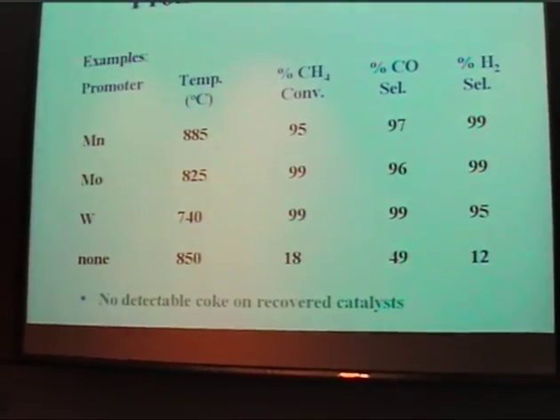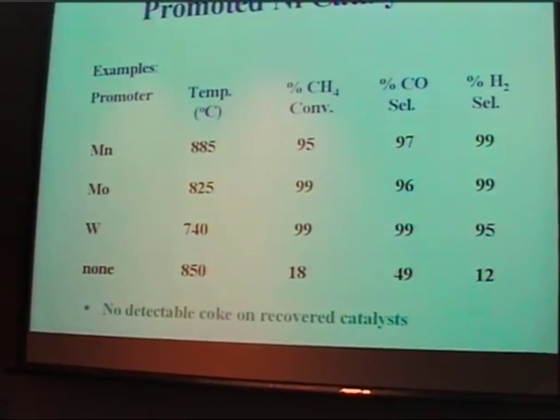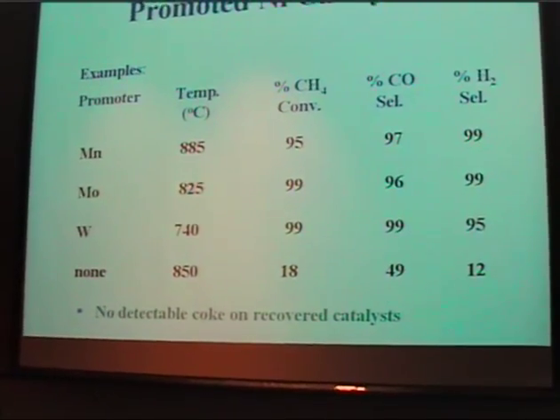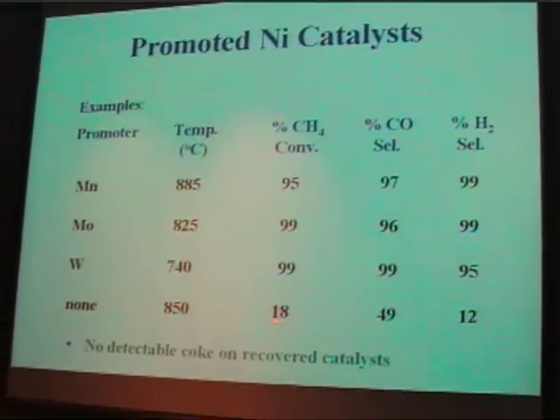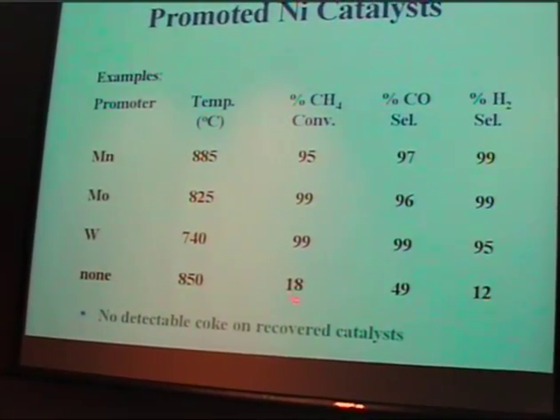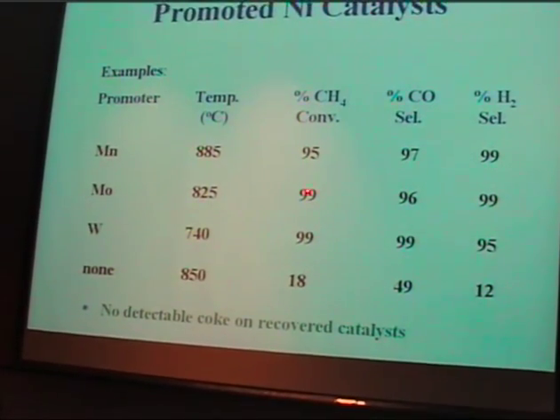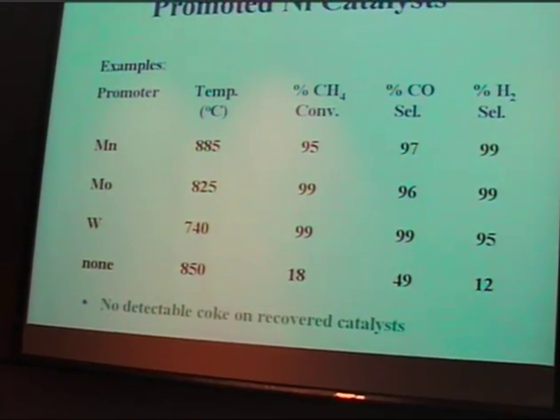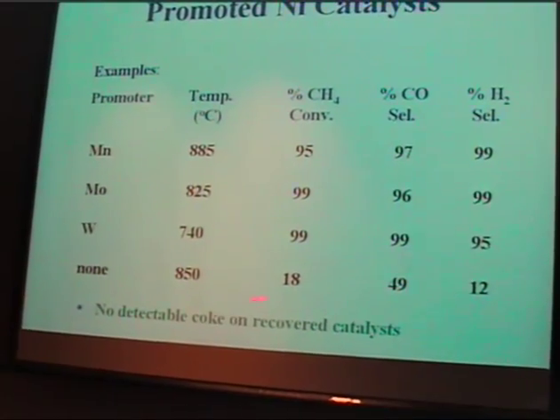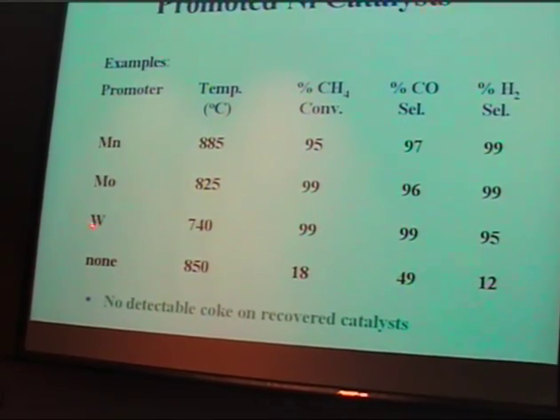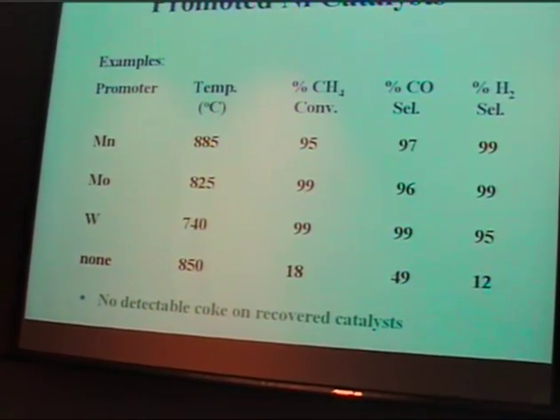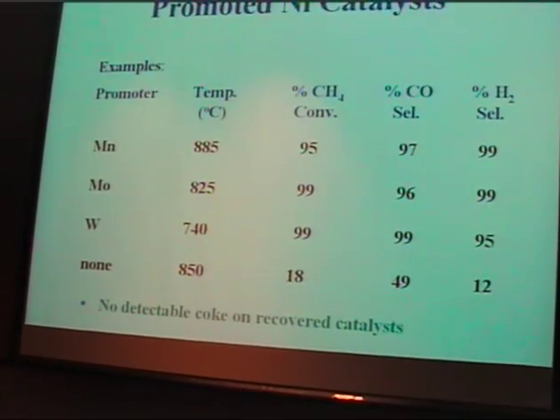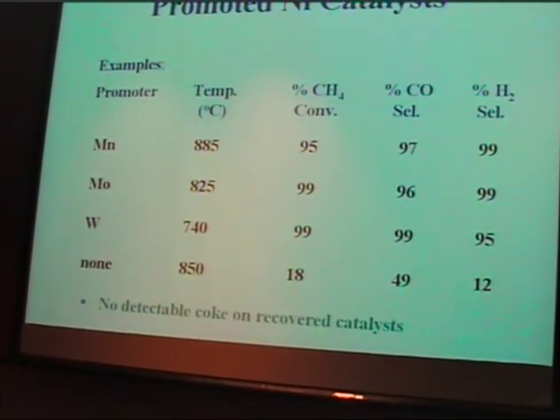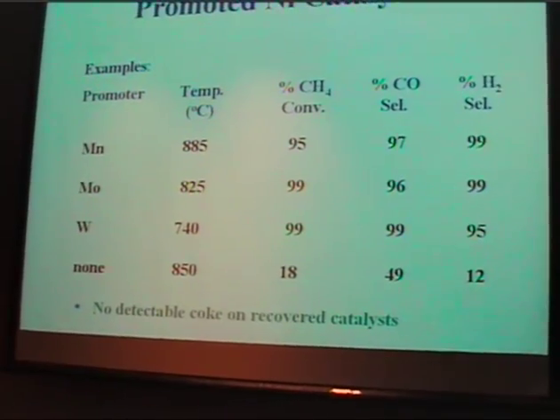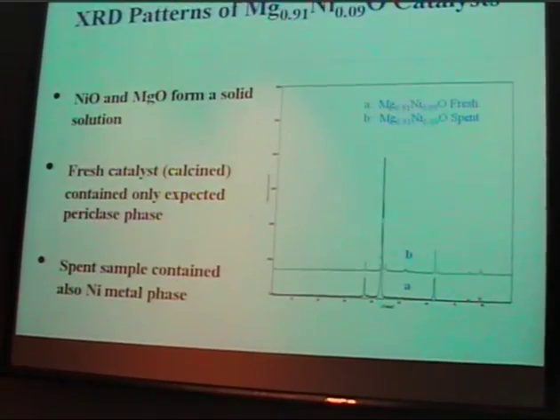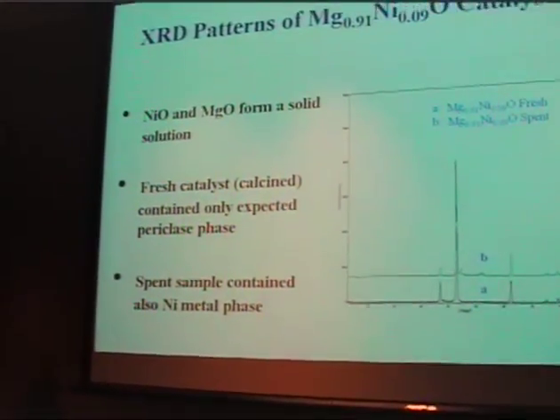And here's the patent data, basically with the promoters shown here versus without the promoters. And you can see the striking increase in activity and selectivity. And basically with the 3 promoters under 1 day of operation, you're seeing no detectable coke. And you'll see later on, without the promoter, you can get up to 1 to 2% under comparable operating conditions.